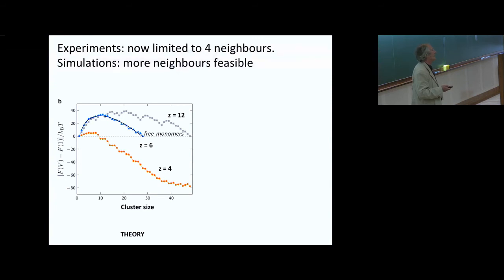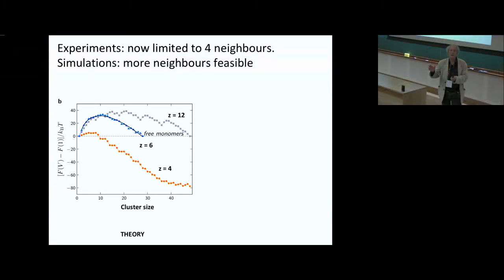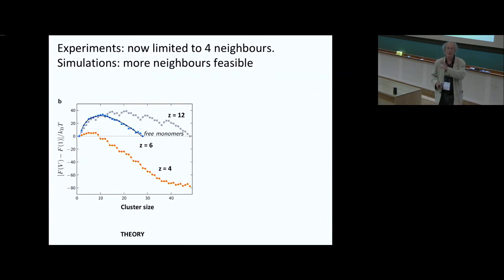So given that you have specific interactions, does polycrystallinity play a role in the sort of barrier you'll see? There's two things. First, we have the specific interactions, but also non-complementary DNA strands can bind, be it more weakly. And so there is, in a sense, a sweet spot where the complementary DNA dominates the process, and you don't yet run into the problem of all the non-complementary strands. If you go to low temperatures, which is what I showed when I get this very strongly polycrystalline sample, that is where your entire process is killed because you have too many non-specific interactions.